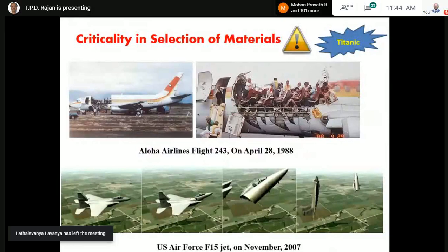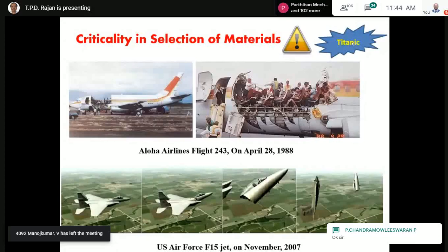And when we select materials for different applications, it's very important that the criteria of selection is also very important. So I think everybody knows about the tragic end of one of the luxury ships, that is Titanic. So what has happened is the steel normally, which is used at room temperature, has very high strength. But the same steel, when it is reduced to very low temperature in the freezing range, becomes ductile to brittle. So in the physical metallurgy of steel, it is called ductile to brittle transition. That means a ductile material immediately becomes brittle when the material is taken to very low temperature.